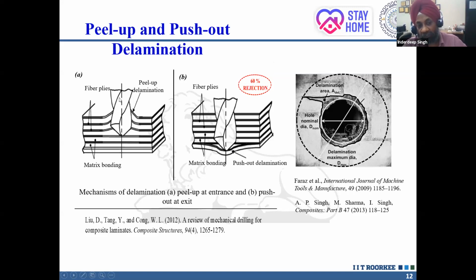You can see this is the first form of damage, second form of damage, and the third form of damage is that you can see fibers being pulled out from the polymer, and then there is damage that is propagating in this direction all around the hole. This we normally call a circularity defect. We want to make a hole like this white circle, but you see all around the hole there is a lot of damage that has taken place.